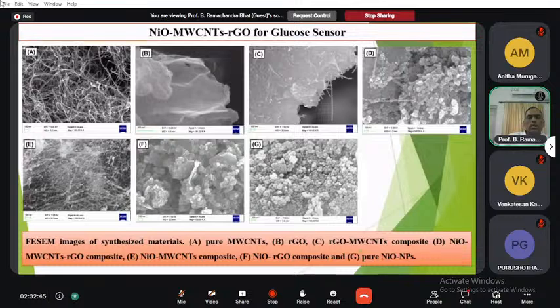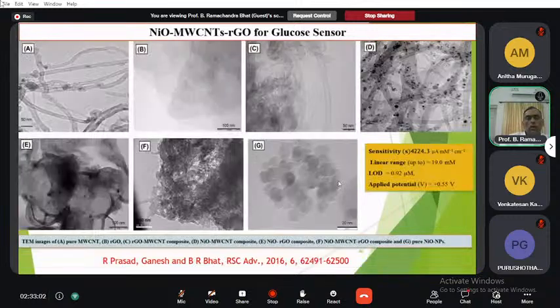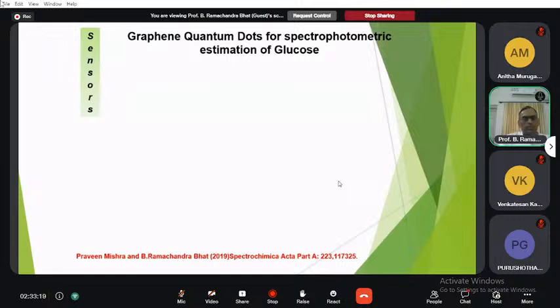So these are some images of the material, that is nickel oxide and multi-wall carbon nanotube, and we have added graphene oxide also to this, and this is the material which is used for again glucose sensors, and the sensitivity is a very good sensitivity of 4244, then a linear range of 19 millimole, and LOD of 0.92, and applied potential of 0.55 volt.